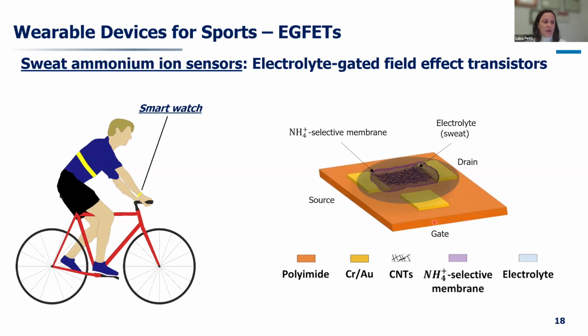You see here the structure of the device, which has planar gate, source, and drain electrodes. It has a spray coated, so again printed, layer of random network of single wall carbon nanotubes, and it has also a membrane because we're interested in selective sensing of the ammonium ion, and an electrolyte, which is clearly leading to the operation of this device, which does not have any solid dielectric as a traditional transistor.